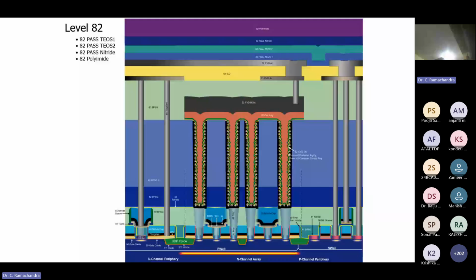For simple devices, it can be 1, 2, 3. Nowadays, it has exceeded 10 in some devices. So that means this whole structure is not more than 5 to 10 micron. If you have a wafer of thickness 700 micron or 1000 micron, only the top 5 or 10 micron consists of your active device. The rest is only bare silicon.